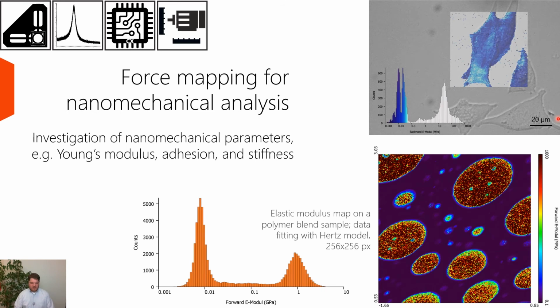Another example is a polymer blend. This is now a measurement that's done in air. It's more of a material science application. We have relatively high elastic moduli, up to a gigapascal here, while, for example, for the cells, they were in the 10 kilopascal range. You can also obtain a map. You see the distribution of different polymers basically within this blend.